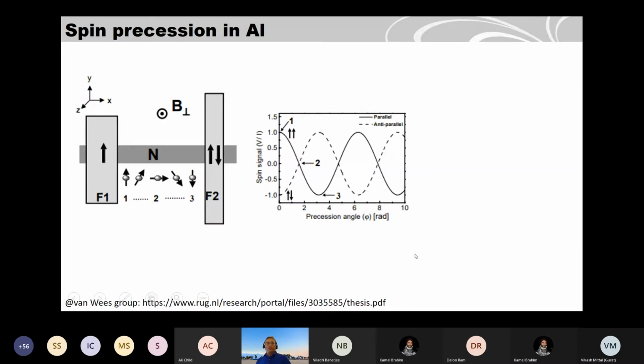So once your spins are injected into graphene, you can detect by changing the magnetization and doing the spin valve measurements, but you can detect also by another method. It's called the spin precession method, Hanle spin precession, because it was discovered by Hanle in the 1930s. When you apply a magnetic field, the polarization of the atoms goes down with applying higher magnetic field, which is perpendicular magnetic field here. So you have a ferromagnet, a non-magnetic channel, spins are going here, and you apply a perpendicular magnetic field. So what will happen? Spins will precess when they are going in this channel, and you will be able to detect at this electrode.